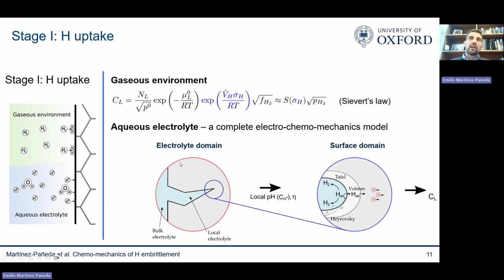In the case of an aqueous electrolyte, problems are much more complicated. You not only need to resolve the surface reactions happening at the interface between the metal and the electrolyte, but also the electrochemistry of the electrolyte, which can be very different inside cracks and occluded chemistries compared to the bulk, where you can do your engineering measurements.